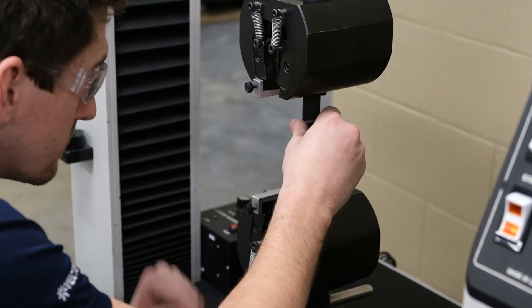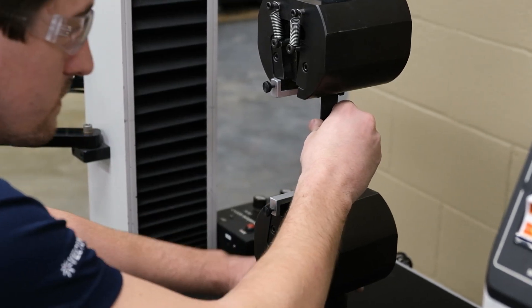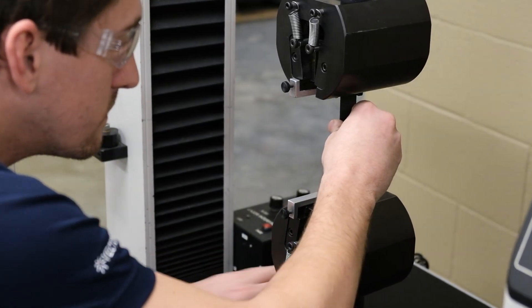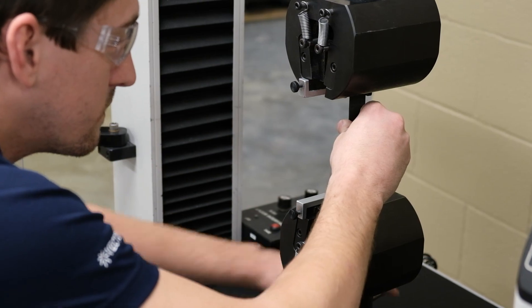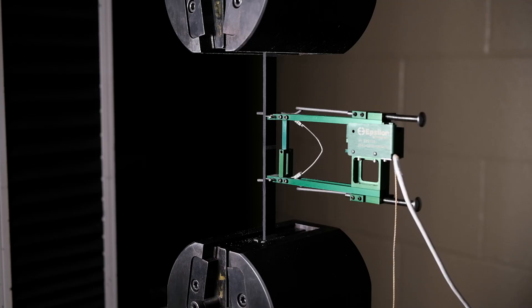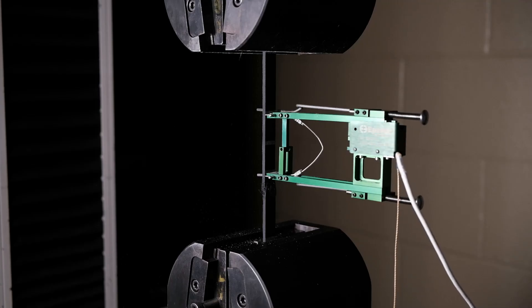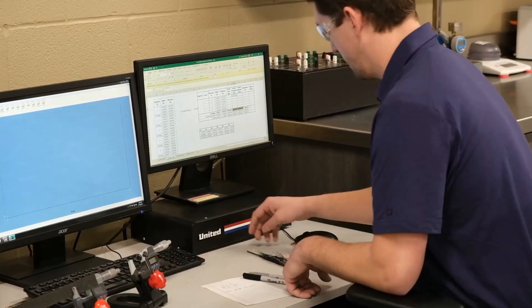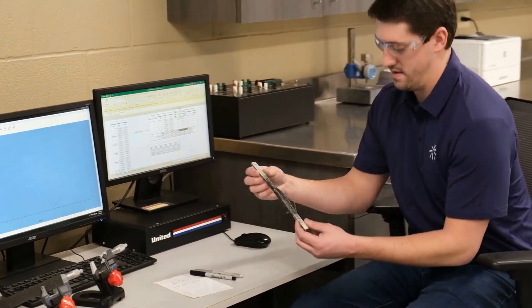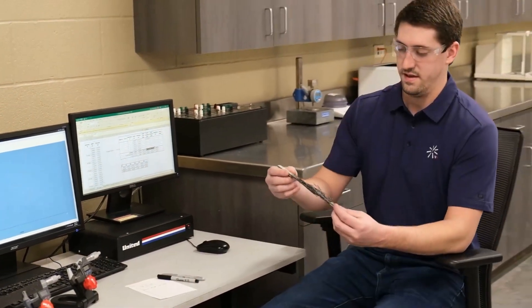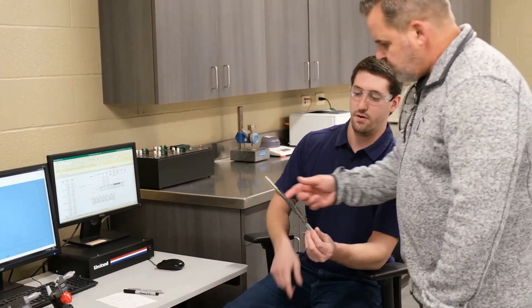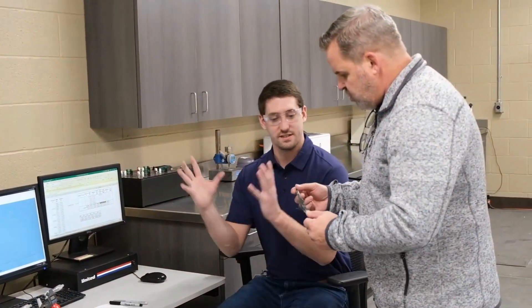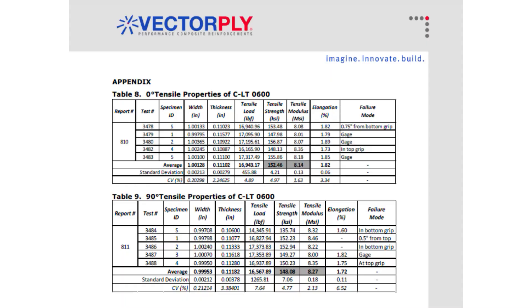Tension, compression, and in-plane shear tests can all be used to characterize either laminate or ply properties. While some composite structures are loaded in-plane, the results of these tests are most useful in establishing properties for analysis and less useful for comparing two laminates. Our test reports will provide the associated tested modulus and strength as well as properties normalized to a specific fiber content. Poisson's ratio, elongation at break, and ultimate load can be provided as well.